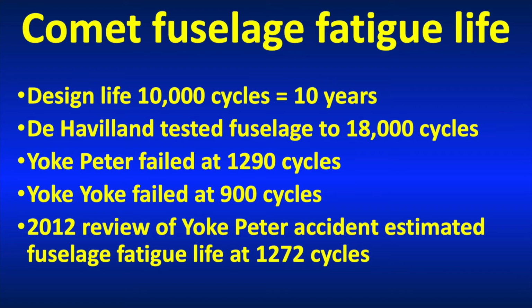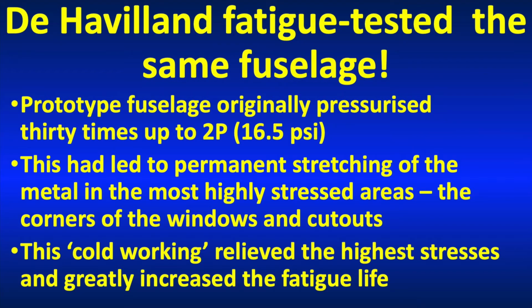But in the light of recent knowledge, Professor Paul Withey of the University of Birmingham in 2012 took another look at the expected fatigue life of the Yoke Peter fuselage, and he came up with a number of 1,272, which is only fractionally below the life at which it failed. So what de Havilland did wrong here was they retested the original fuselage, and for reasons that will become apparent in a moment, because they took the fuselage up to twice the pressurisation pressure 30 times, this had actually led to permanent stretching of the aluminium in the most highly stressed areas. And this is called cold working, which wasn't that well understood at the time. But that stretching relieves the stresses in that area and greatly increases the fatigue life.